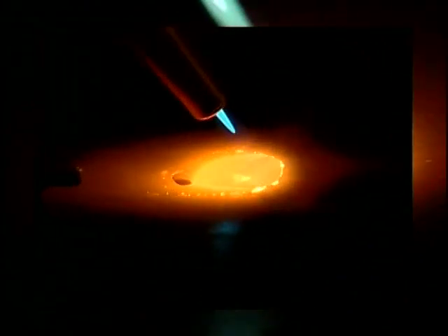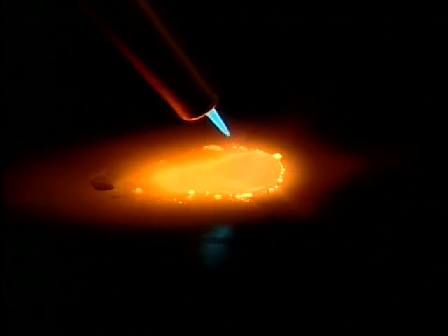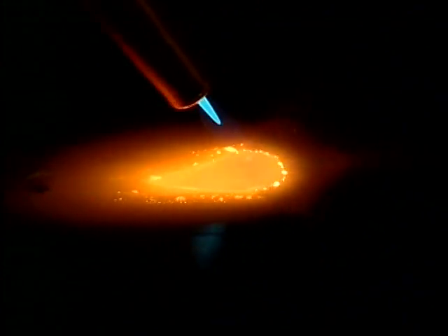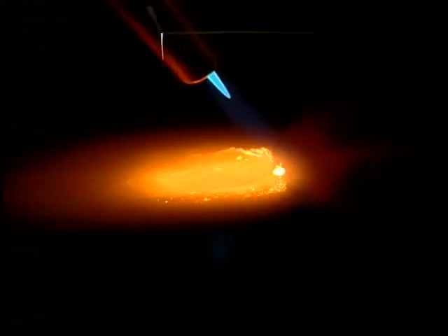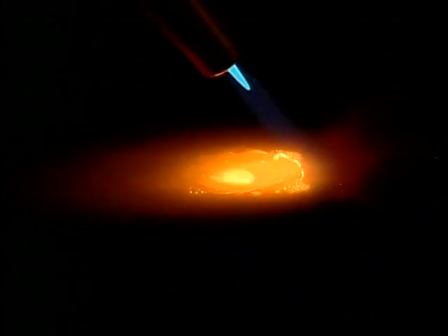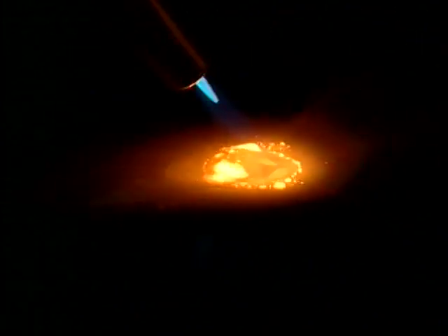The oxidizing flame burns at a higher temperature. It produces an iron oxide foam around the molten weld pool. There is a steady stream of sparks that can be seen flying from the weld pool. Welds made with an oxidizing flame tend to be weak and brittle.